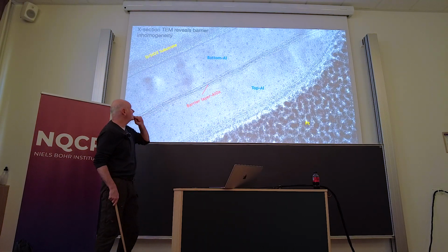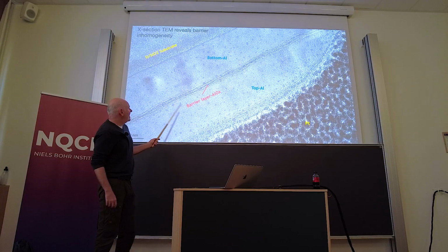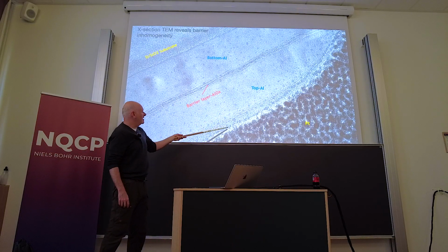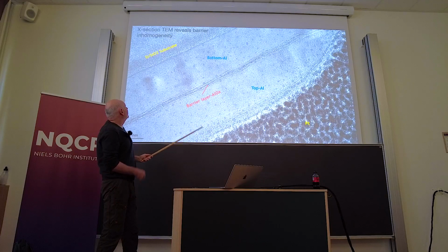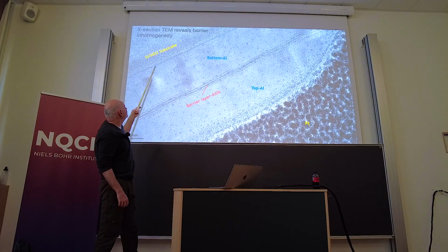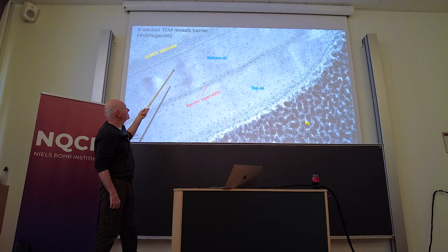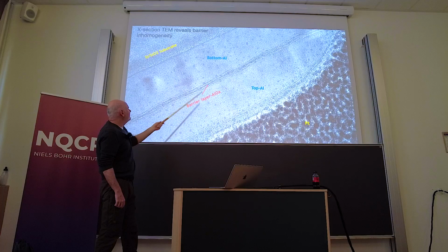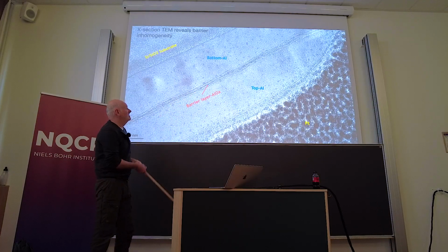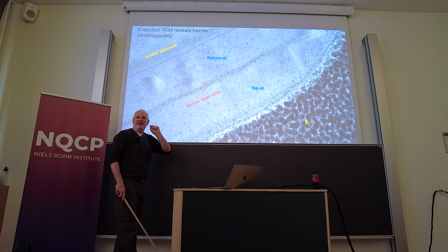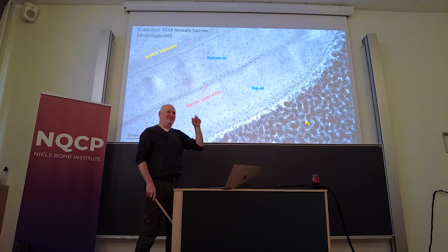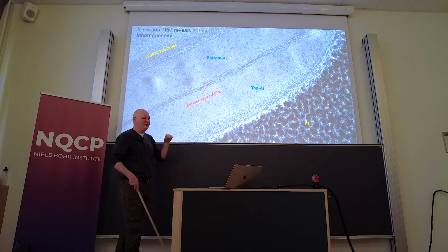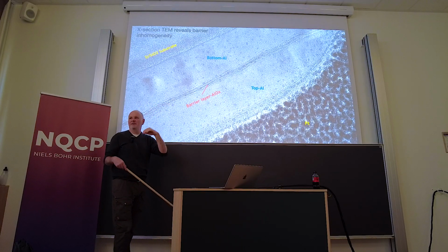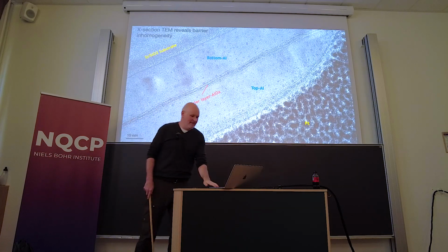And this is actually a nicer junction. But you can see that, one, there's aluminum oxide coating everything. In this particular case, this is actually on silica. So you don't see it here, but you also get silica at the interface between the aluminum and the silicon. And then the barrier layer of the aluminum oxide is not a nice, straight, perfectly even slice of cheese. It is something that's very rough, and it's determined largely by the grain structure of the aluminum that it grows on. And so that's not great.